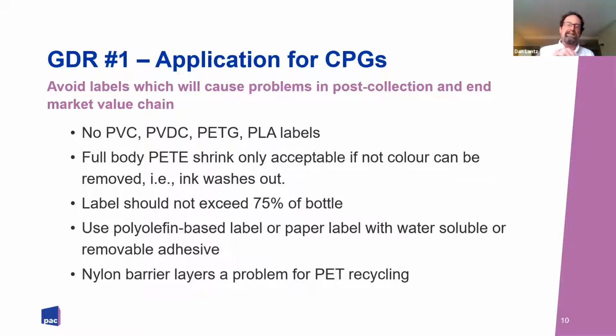And so the nylon that's in there, just speaking with an end market in Ontario, Ice River Springs, call them out, they're doing a great job, and talking to Crystal, the nylon barrier layer is really starting to cause a problem for them because nylon doesn't melt at the same temperature as PET. It melts at a lower temperature. And so when you get up to PET temperatures, it starts to burn. And of course, that causes problems for the quality of the recyclate that they're making their new recycled PET bottles from. So we need to find an alternative to the nylon barrier layers in order to maximize the value, again, consistent with the GDRs, maximize the value of the PET.